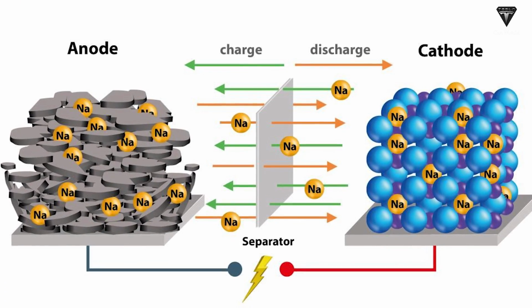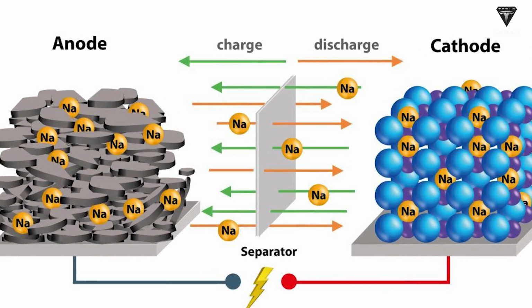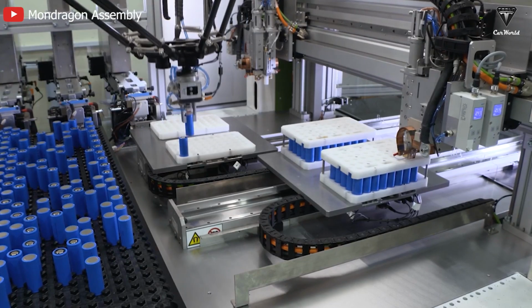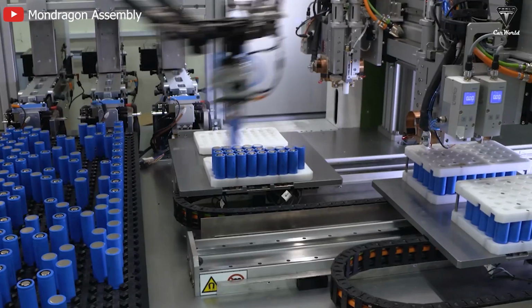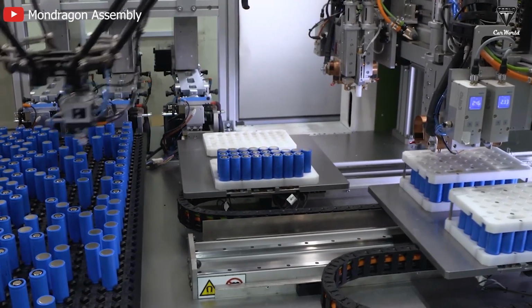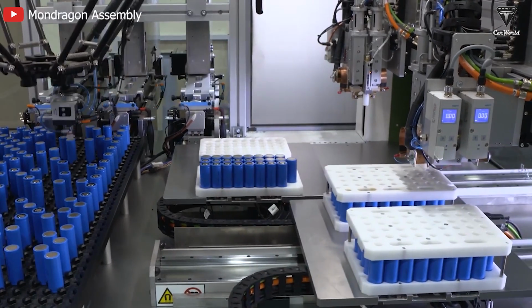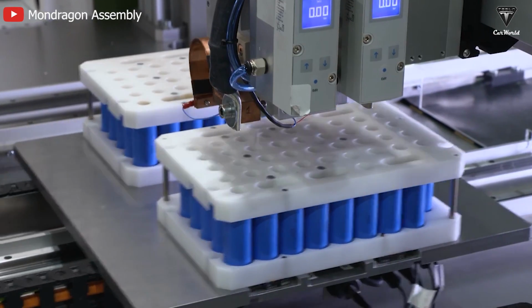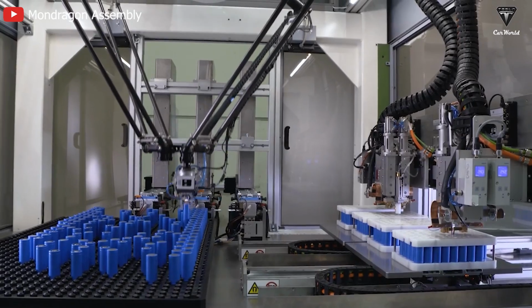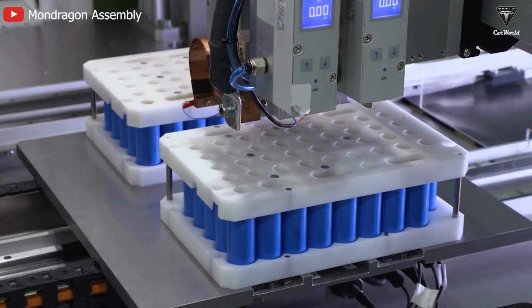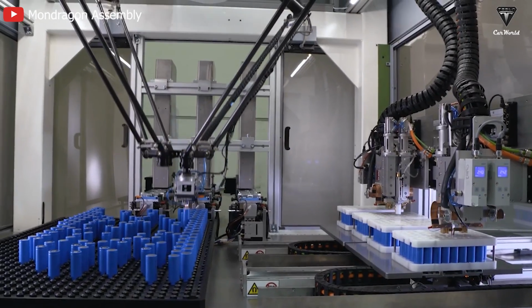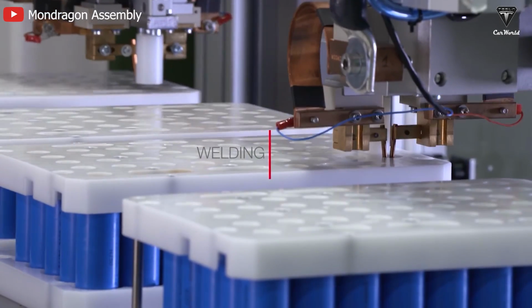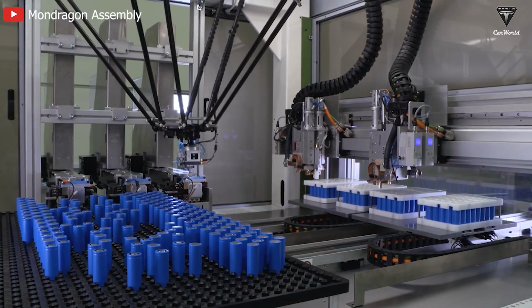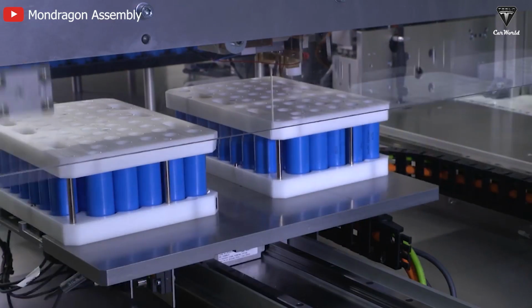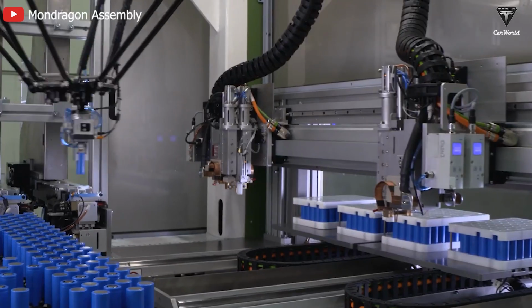Sodium-ion batteries can also be discharged to 0 volts during transportation, avoiding the risk of thermal runaway, something that's difficult for lithium-ion batteries. The fact is that lithium-ion batteries usually operate optimally at 15 to 35 degrees Celsius, and when the temperature drops below 0 degrees Celsius, battery capacity will decrease rapidly. For example, at minus 20 Celsius, the battery capacity is only 50% of normal.